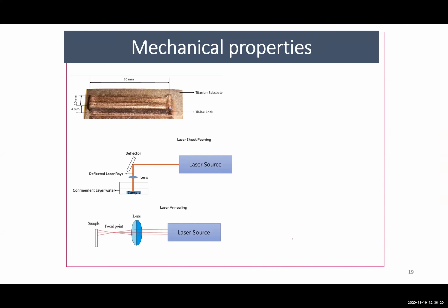So for that, we went for some concept called laser shock peening and laser annealing, because in the case of additive manufacturing, here I had a metal powder. So I'm just melting that metal powder and I'm manipulating it. When I melted my metal powder and manipulated it, obviously there is going to be a certain amount of defect which will get involved. Some of the major defects which we observed: there was a random crystallization. That was one thing. In the meantime, there was a random stress which was getting induced.